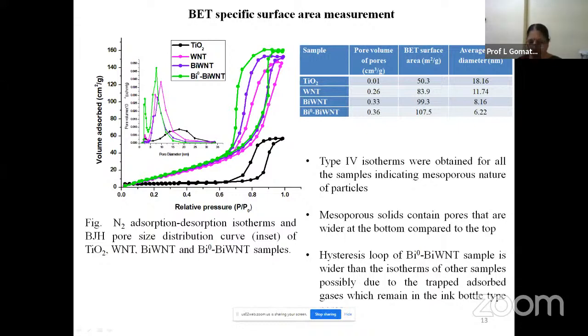But what we have to observe is that every sample has shown hysteresis loops, and the area in between these hysteresis loops is higher for the Bi0 BiWNT sample. This implies that though there are capillary type pores, these pores are something special. We call them ink bottle type pores. That means at the beginning they will be narrow, and at the bottom the pores are very broad.